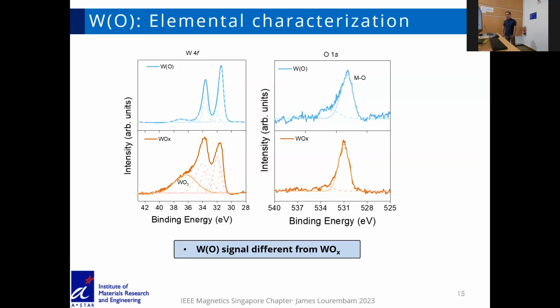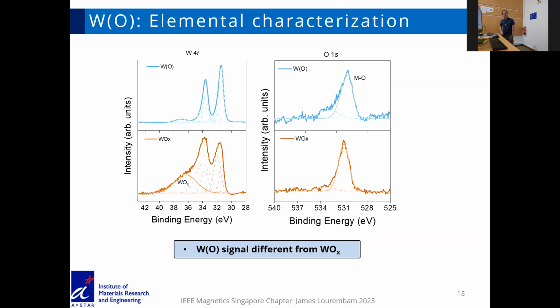If we look at the XPS of this system, the left plot is the XPS data of tungsten spectra, and the right is for oxygen spectra. The two big peaks at around 34 and around 32 are mostly coming from the metal tungsten peak. The top and the bottom plots are for our tungsten multilayer, and the one at the bottom is a tungsten oxide compound.